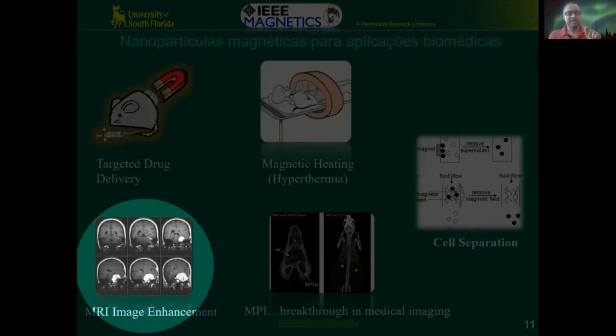Now, if you put magnetic nanoparticles inside the area that you want to image, like the cell that you want to image, it turns out that the fringing fields from the nanoparticles interfere with the T1 and T2 relaxation times, NMR relaxation times. And because of the difference with and without the nanoparticles, you can actually get a better contrast. So it has been demonstrated. This is an area where there's been a lot of work, but it's clearly shown that magnetic nanoparticles are very useful for improving the contrast in MRI images.